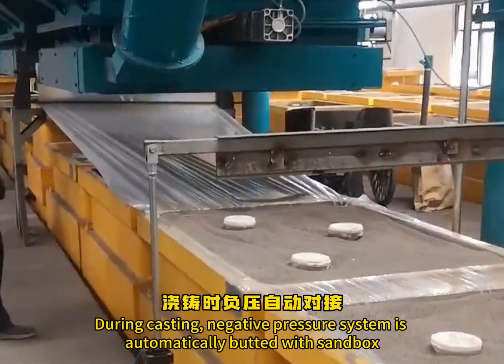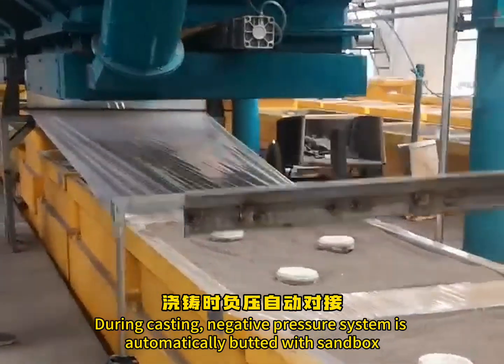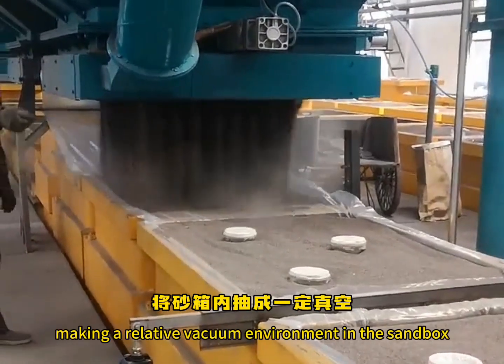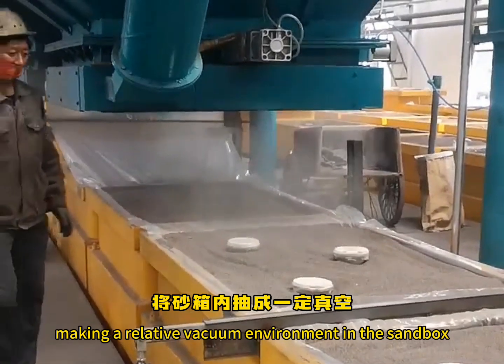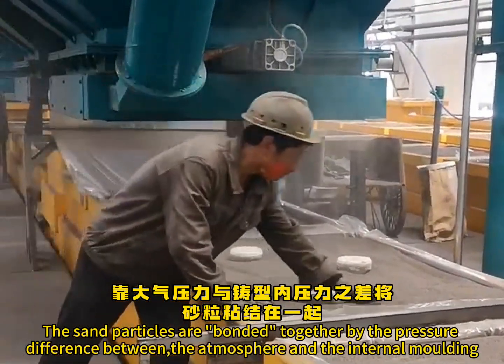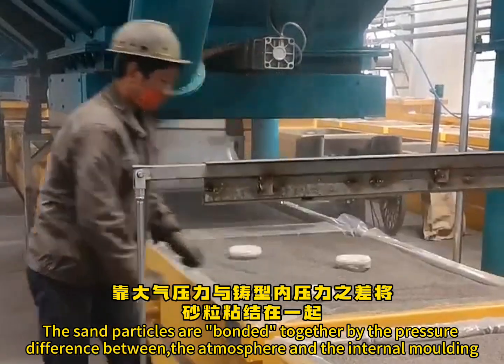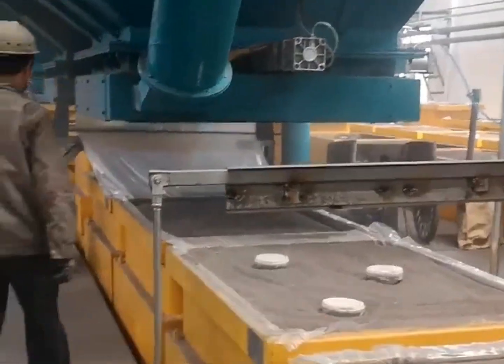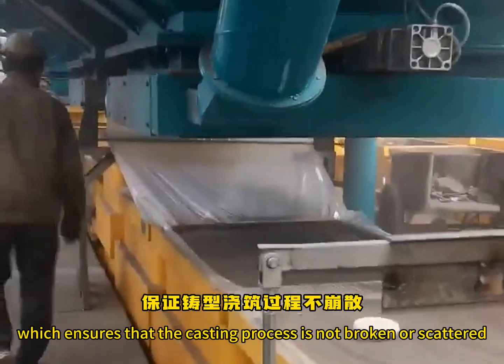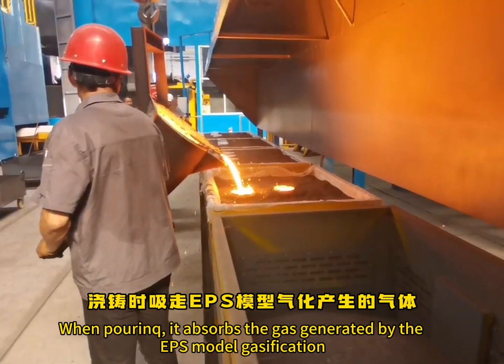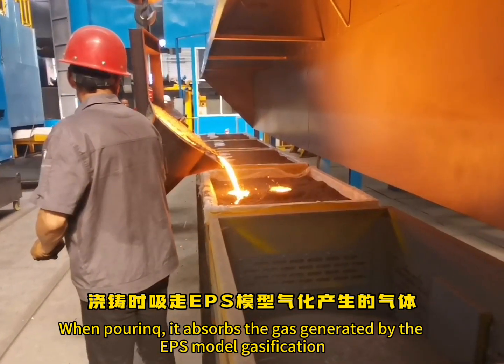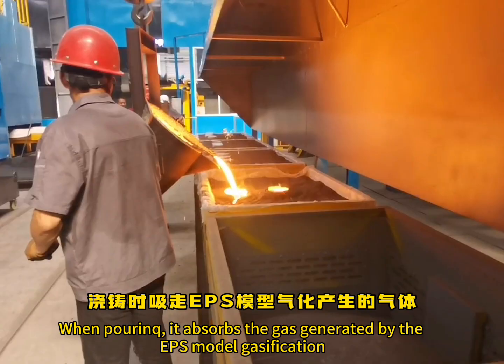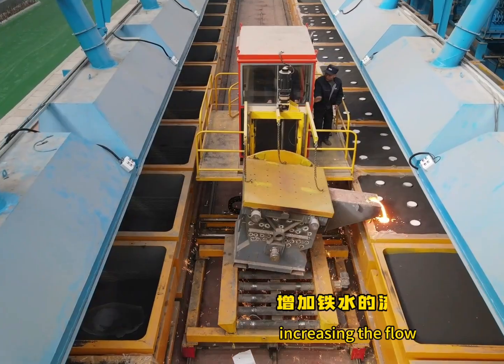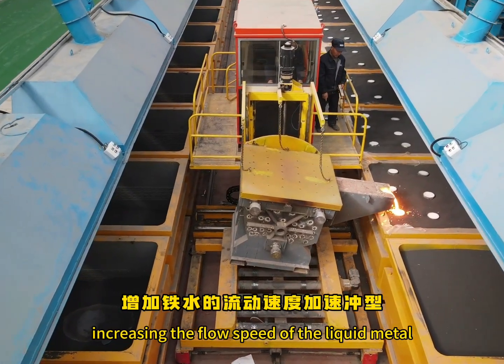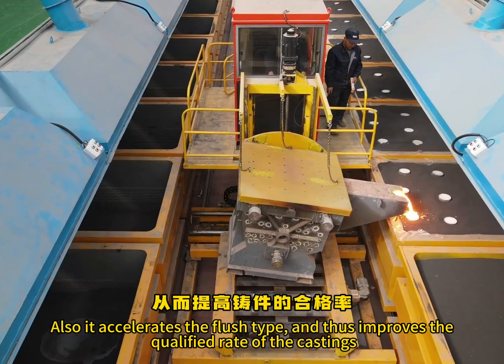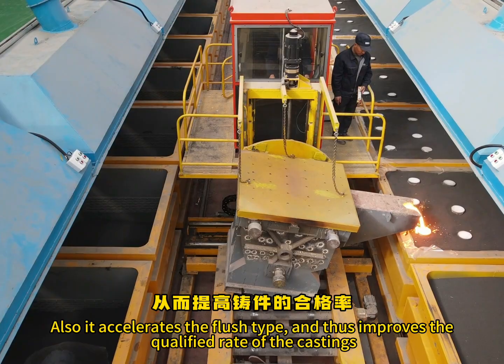During casting, negative pressure system is automatically butted with sandbox, making a relative vacuum environment in the sandbox. The sand particles are bonded together by the pressure difference between the atmosphere and the internal molding, which ensures that the casting process is not broken or scattered. When pouring, it absorbs the gas generated by the EPS model gasification, avoiding blowhole in the casting, increasing the flow speed of the liquid metal. Also, it accelerates the flush type, and thus improves the qualified rate of the castings.